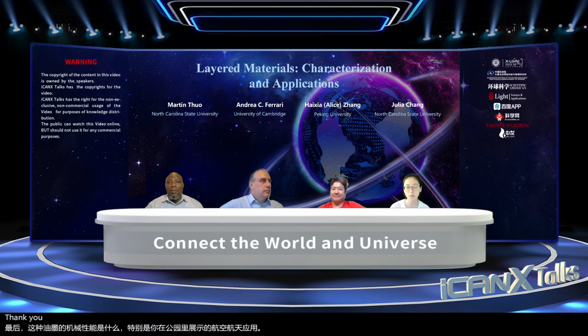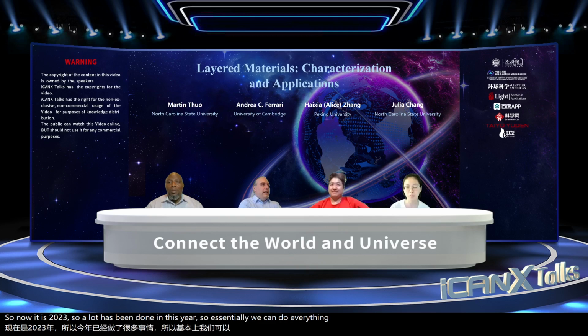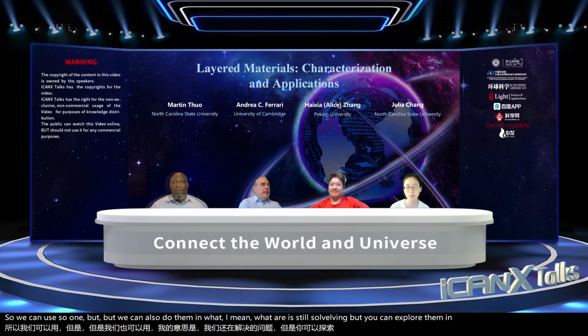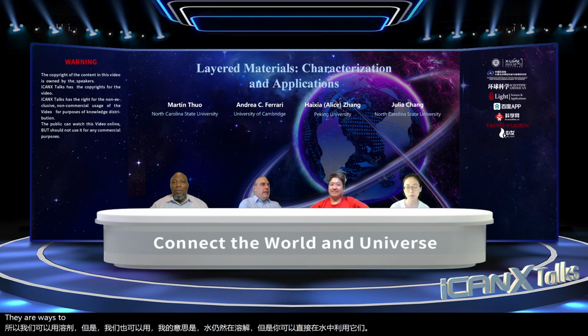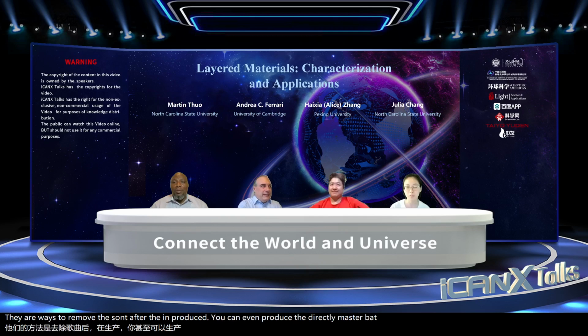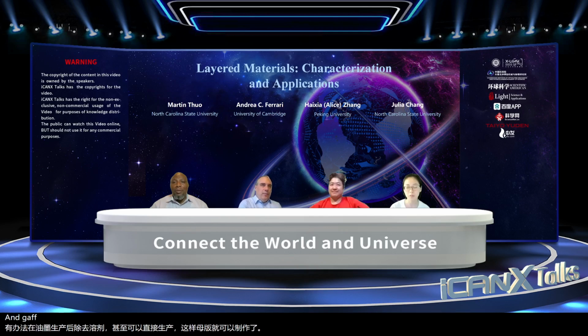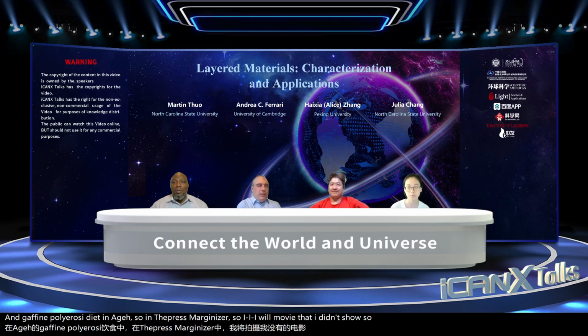Thank you. So as mentioned, the inks started in 2008. So now it's 2023. So a lot has been done in this time. So essentially we can do everything now. So we can use solvent, but we can also do them in water. I mean, water is still a solvent, but you can exfoliate them in water directly. There are ways to remove the solvent after the ink is produced. You can even produce directly master batches. So you can make graphene polymer composites directly in HPH, the high pressure homogenizer. I have a movie that I didn't show.